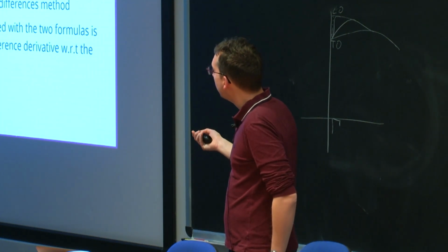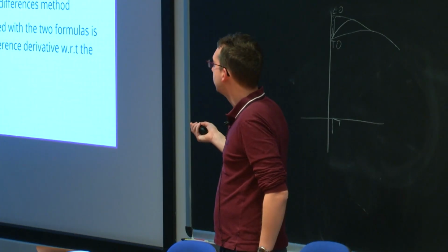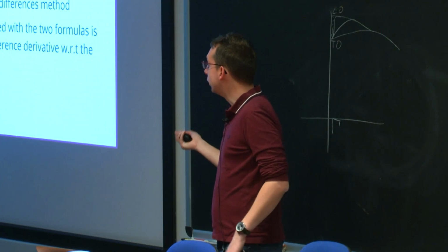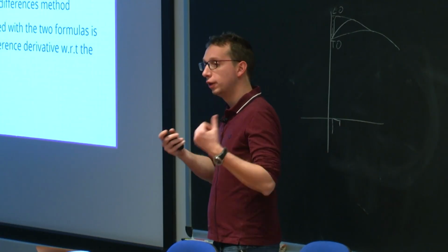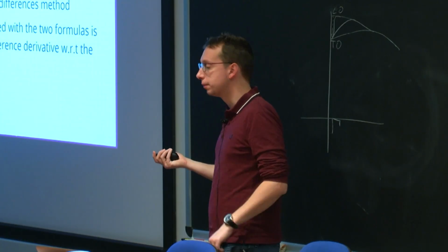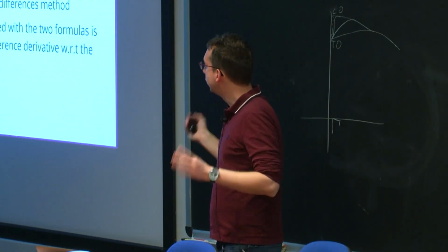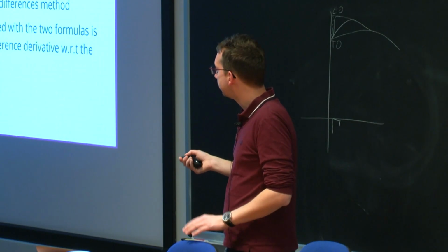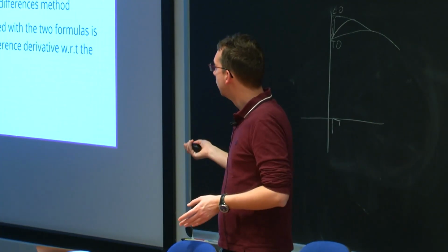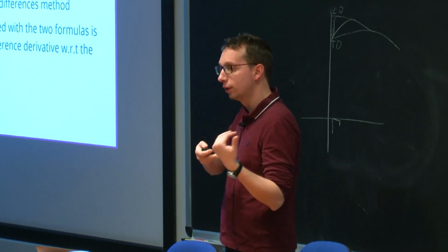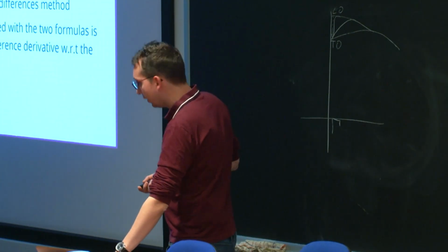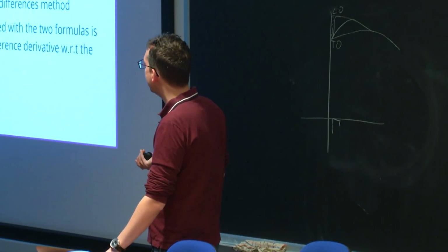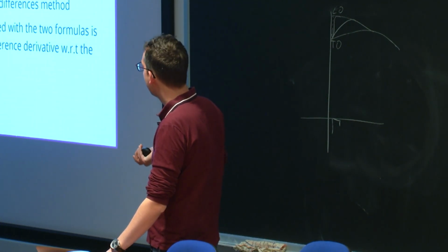However, from practice, I noticed that this method usually converges faster than doing the finite differences with respect to the k-point grid. I don't think it's a theorem, so it depends a bit on the system. But in the example, I could see you required fewer k-points to get the proper Raman tensor with this expression than doing finite differences.